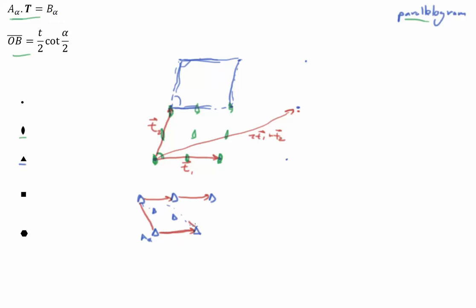I already see a unit cell here. I'm going to subdivide it just to see it more clearly, composed of two equilateral triangles that are sharing a side. And this is described as a rhombus. This is a 120-degree rhombus, where this angle here is 120 degrees. This length, if I call it L, is the same as this length. This is 120 degrees. These are each 60 degrees. So this is a 120-degree rhombus lattice, and that is our next kind of lattice that we're going to see.